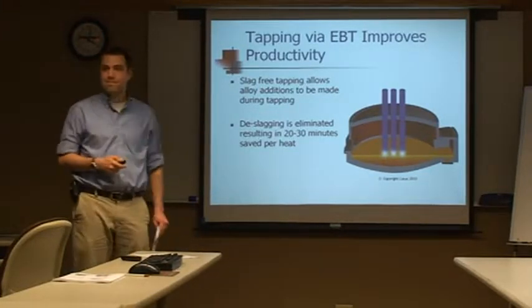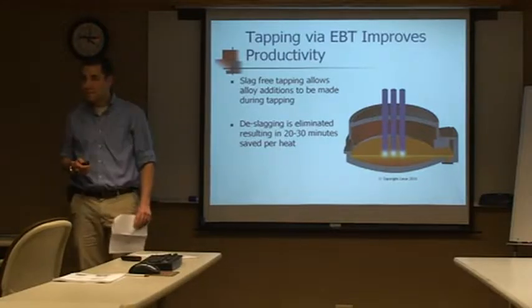So you're not draining it 100%? Well, that gets back to the third point. I didn't want to jump too far ahead when we were answering your question. But we have to leave 5 to 10 tons of liquid steel in the furnace to avoid vortexing over that oxidized slag. So for the next heat, we have this scrap coming in, but we already have essentially 5 to 10 tons of that next heat already melted.